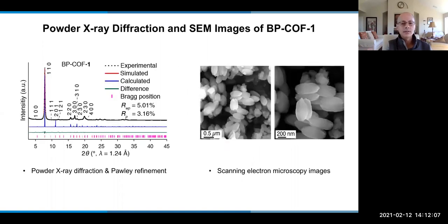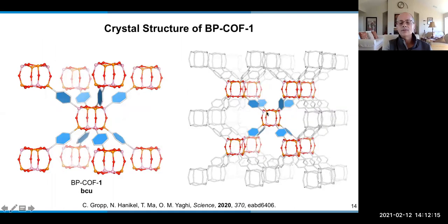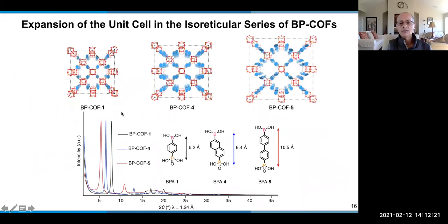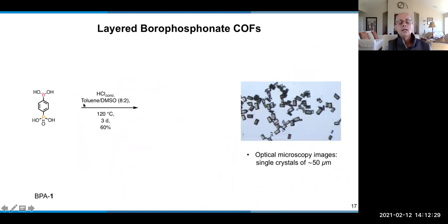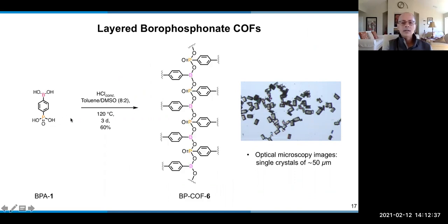This is the powder diffraction pattern, and this is what the structures look like. This polycubane, this is the boron phosphorus linked by the organic polycubane structure. And as I said, you can make the expanded analogs, and you can see that in the X-ray powder diffraction, expansion of the unit cell. And if you add an acid to it, like HCl, you can turn that cubic structure into an infinite SBU, or an infinite connectivity of boron, oxygen, phosphorus, boron.